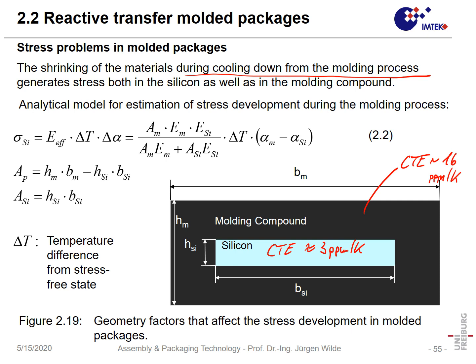First of all, how can we determine stress? We can say in cooling down, we develop a so-called thermal strain. And that thermal strain is proportional to delta alpha, delta T. So the thermal strain will be the higher, the more we cool, and will be the higher, the larger the difference in CTE between silicon and molding compound.